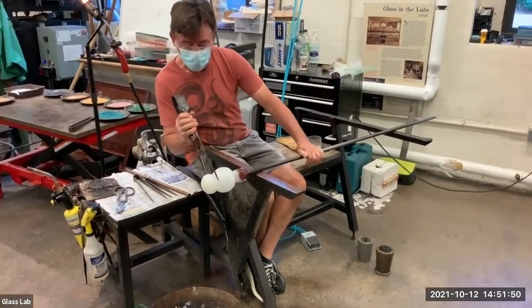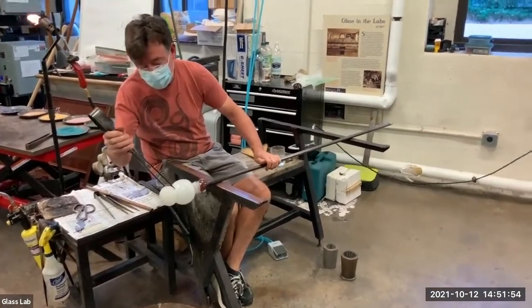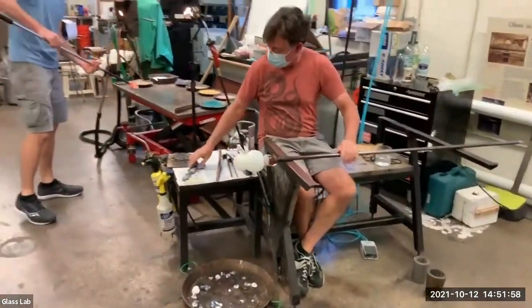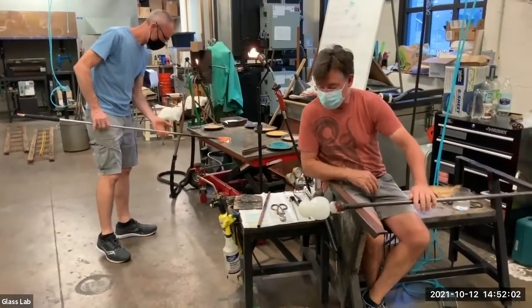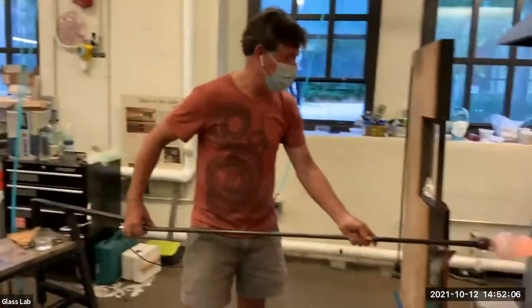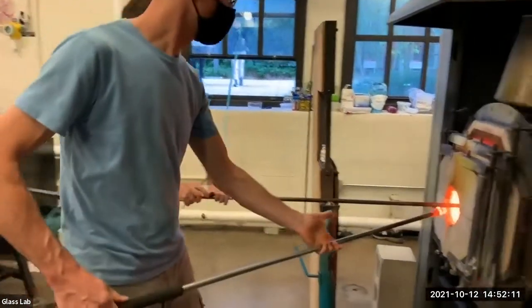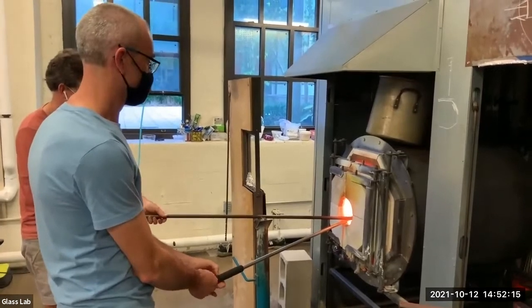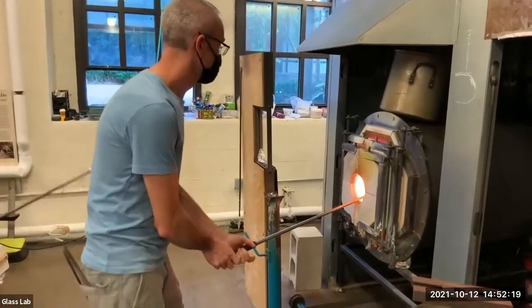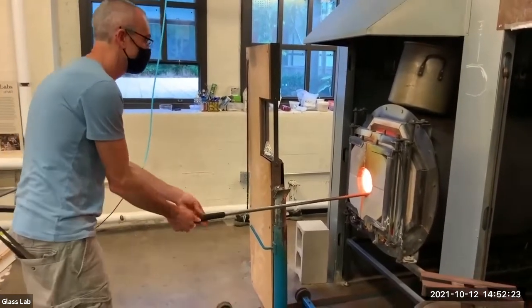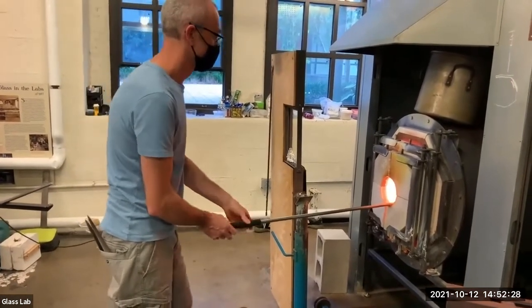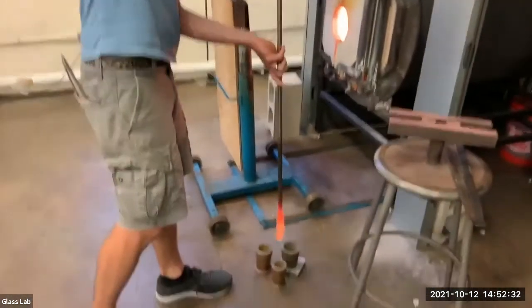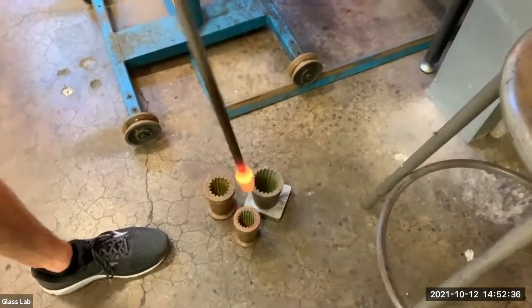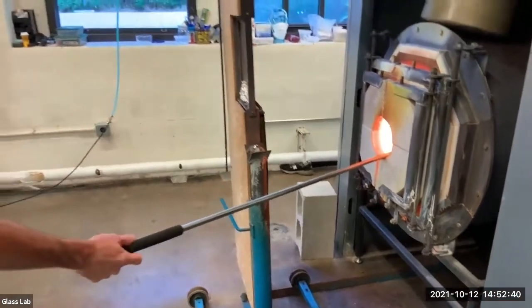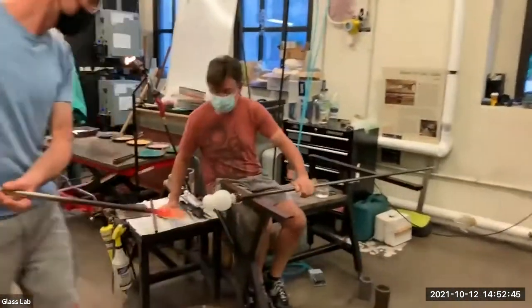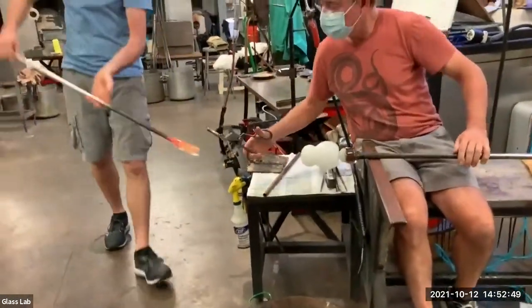We're just going to hang out and let it get to something closer to about 900 degrees. And I'm paying attention to what Whitney is doing now, because I will have to take a flash or two before I get this stem. If I wait too long between heats, the pumpkin can get too cold and crack. And that's happened to me many times. And flip.